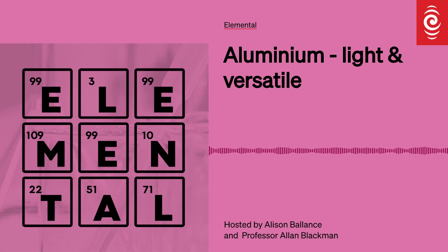No, indeed you don't. And it's not like metals such as, let's say, gold or silver or copper, which do occur naturally in their metal form. Aluminium really likes oxygen. So you take aluminium metal with oxygen and they react very vigorously and very rapidly. Now, the reverse process, getting the metallic aluminium out of bauxite, is difficult. Now, it can be done chemically, and that was the way that it was first isolated way back in about 1827. But that is not an ideal process. The easiest way to do this, to take the aluminium out of bauxite, is to use electricity.